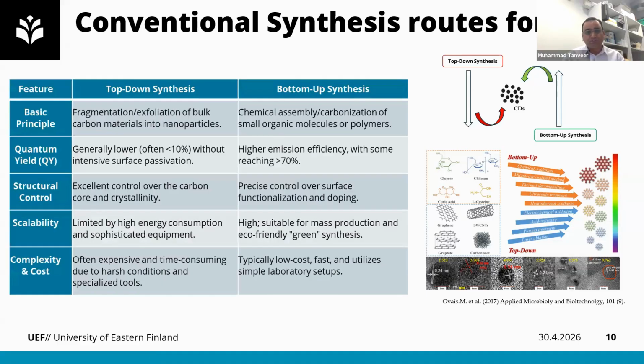If we compare these two systems, then we can distinguish them on the basis of their principle. Top-down is basically fragmentation of bulk carbon material into nanoparticles. But in the case of bottom-up, we are going from nucleation to the particle stages, like chemical assembly or carbonization of small organic molecules that can be enabled to form a large particle. As far as quantum yield is concerned, top-down synthesis routes can provide a very low quantum yield, but in bottom-up, we can have a quite high quantum yield. And for structural control, top-down can control the carbon core and crystallinity, and bottom-up can tune the functionalization and doping features.